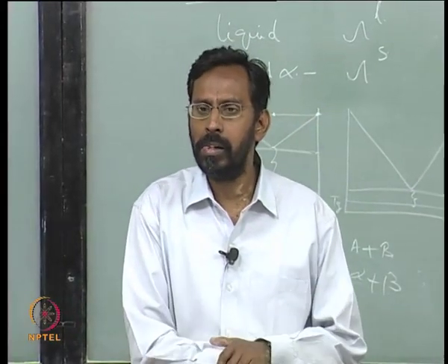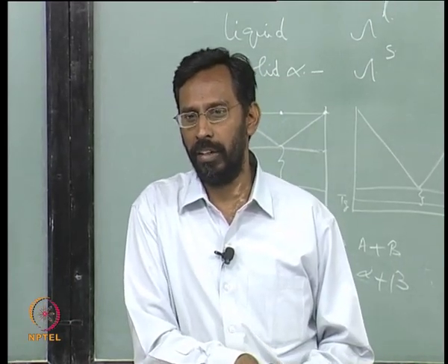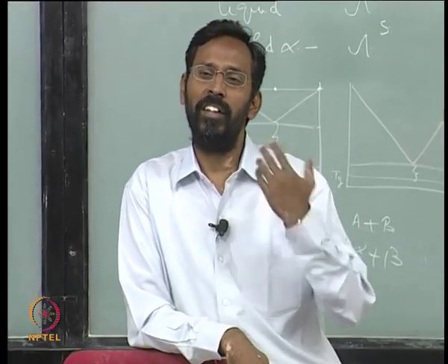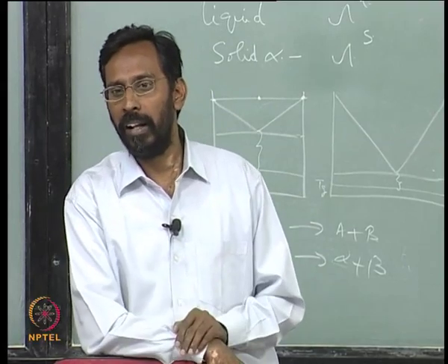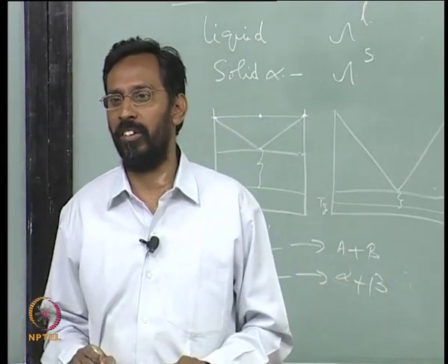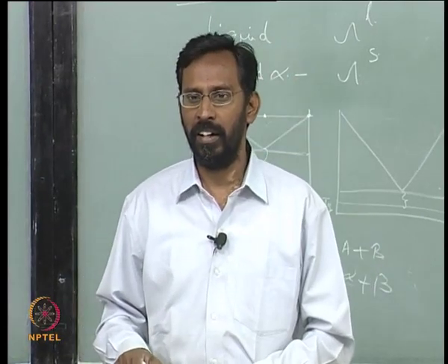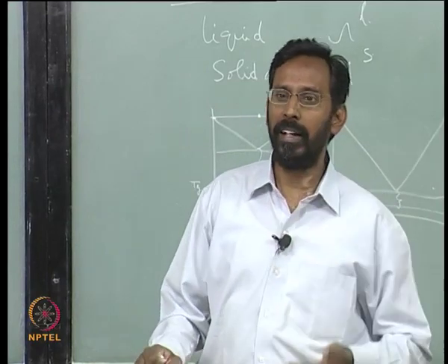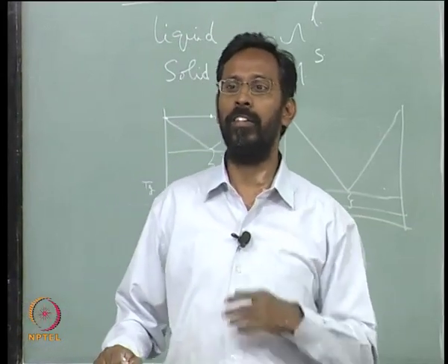Pure iron, okay. It is because of the magnetic transitions, in principle, that iron is BCC at room temperature and then changes to FCC. In fact, if you carefully observe most actual metals, when you go to a higher temperature, the phase that is more stable is the one with a more open structure. You regularly see this happening in, for example, titanium, where the high temperature phase is a BCC phase. In most structures the high temperature phase is a BCC phase. Even in ceramics like barium titanate, the high temperature phase is a cubic phase and the low temperature phase is a tetragonal phase.